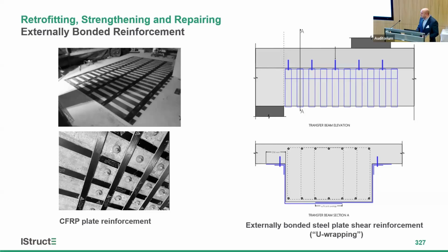they are bonded with resin adhesive, which has a low limiting temperature, and this needs to be considered quite carefully. If you need the externally bonded reinforcement plates to work in the fire, you need quite a lot of fire protection, probably about 100 millimeters of fireboard, and normally that requires a secondary structure to support it, and it's quite difficult to implement.